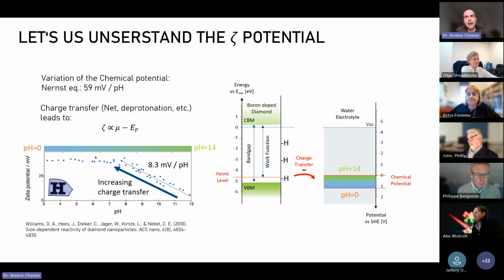And so you're right to say that in the classical picture, if we have nitrogen doped nanodiamonds, the Fermi level should be very much closer to the conduction band. Yet there are also so many defects in the nanodiamond that for me it's very hard to know exactly what is the kind of charge carriers in it. And if you look at the literature and at the measurement of the Fermi level on nanodiamonds, you can find about everything. You have huge fluctuation of the position of the Fermi level depending on the kind of nanodiamond, the way the Fermi level was measured, etc. I would say you're right, but I'm not sure we can be that strict about the position of the Fermi level according to the nitrogen defects, if that makes sense.